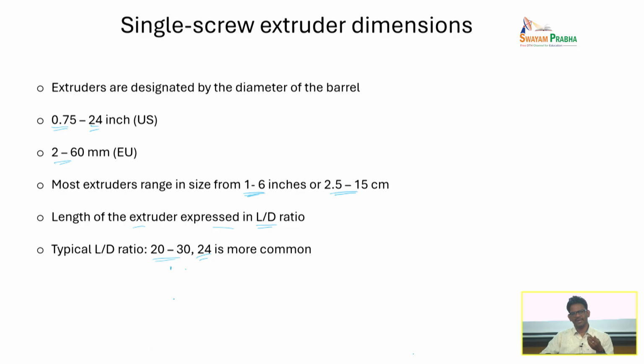So when you see a paper on extrusion of a polymer material, the extruders are basically characterized. We use an extruder of a particular diameter, let's say 1 inch, and with an L by D ratio of 20, and then they will also say that in the barrel the temperature distributions are in the feed zone 120 degrees Celsius, in the compression transition zone the temperature was this, and in the metering zone the temperature is something. So we specify at least 3. It can be actually even more than 3 also.